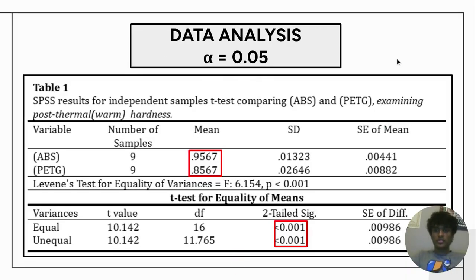The results for the thermal hardness analysis show that in terms of ABS, the mean was 0.9567, and for PETG, it was 0.8567. This was measured in hardness units, and the p-value was below 0.001, which is far below the alpha threshold of 0.05, indicating there is a statistical significance between these values. It also goes to show that ABS performed better than PETG did within this test.